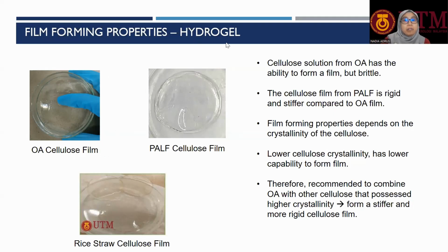In this case, hydrogel. So here are the three examples of the film form. And here is the explanation for each film form. So the cellulose solution from OA has the ability to form film also, as shown here, but it is quite brittle. So here is the PALF cellulose film, and as compared to OA, it is stiffer.